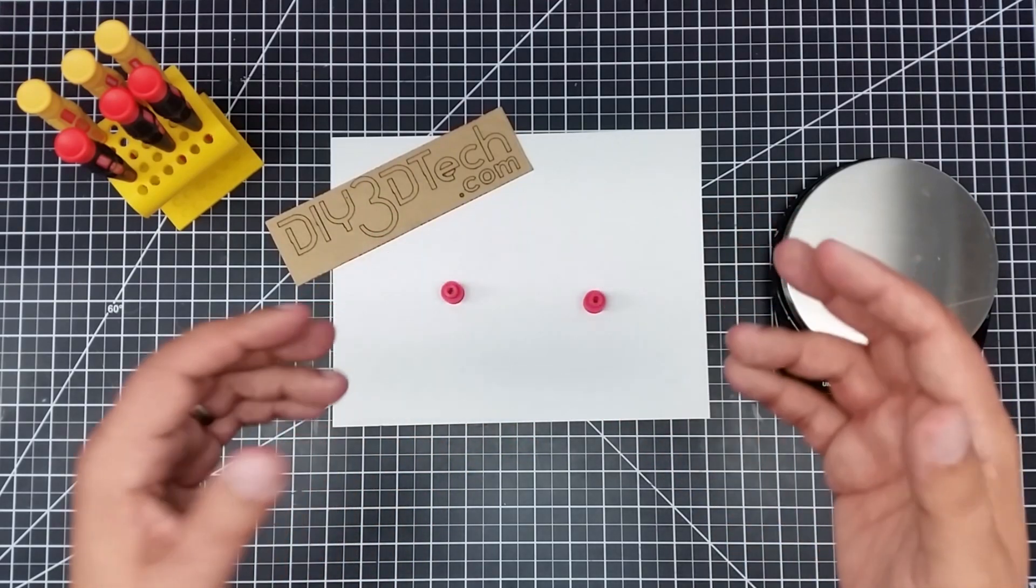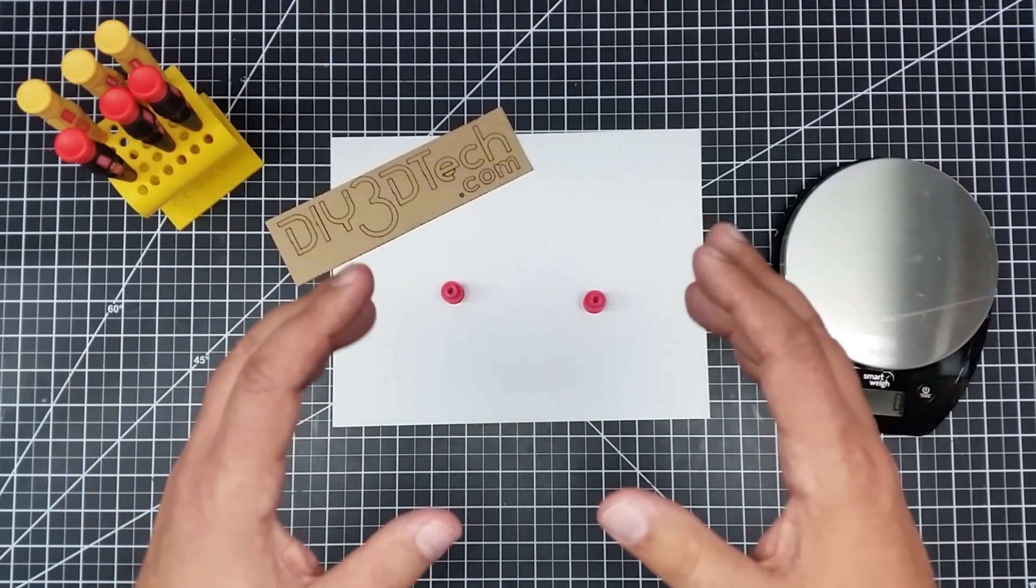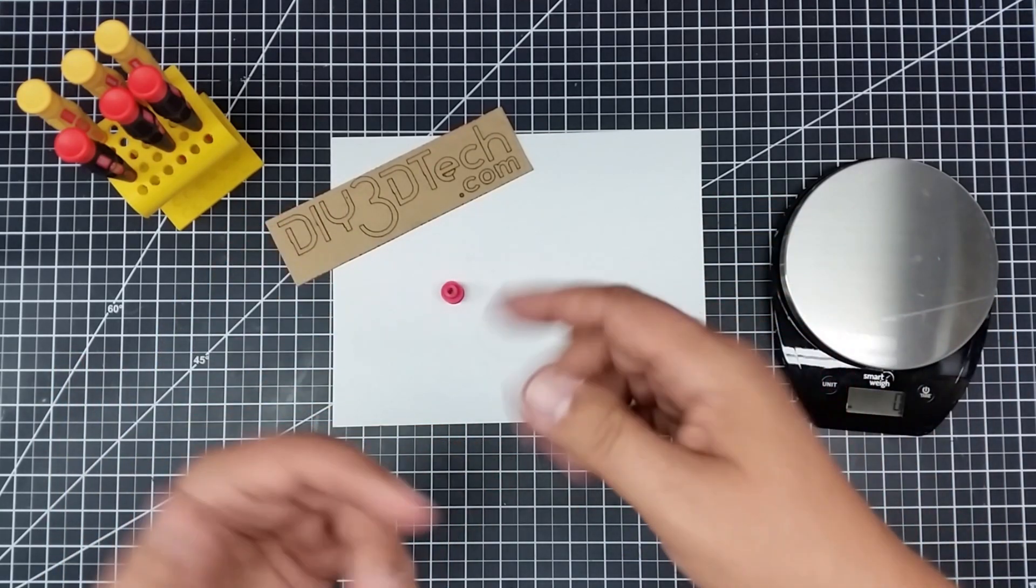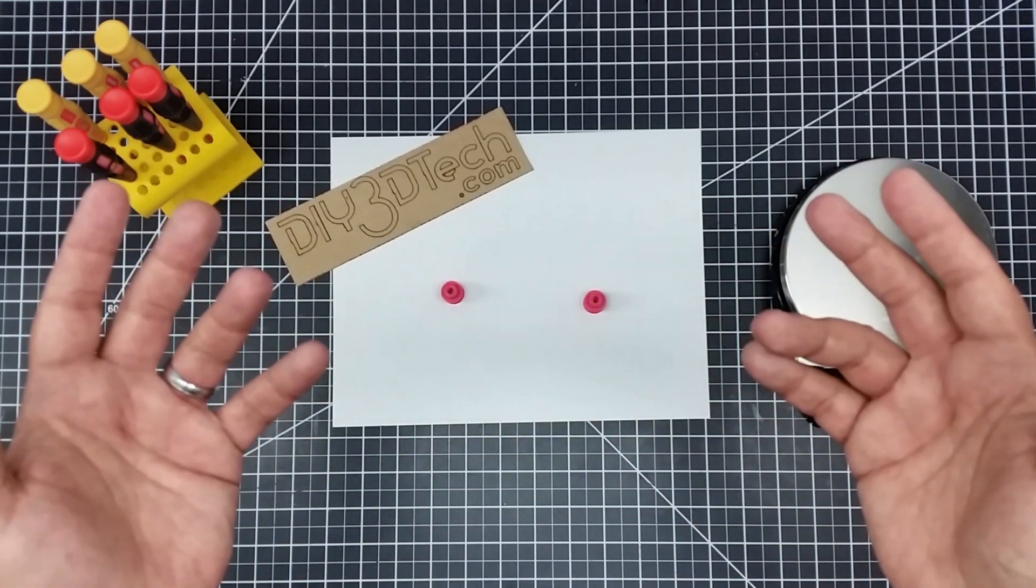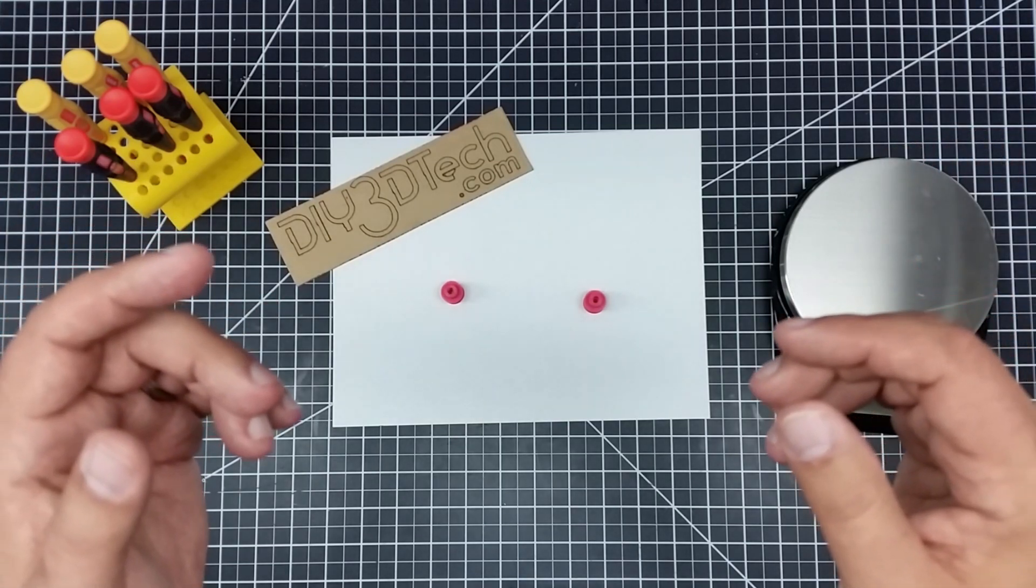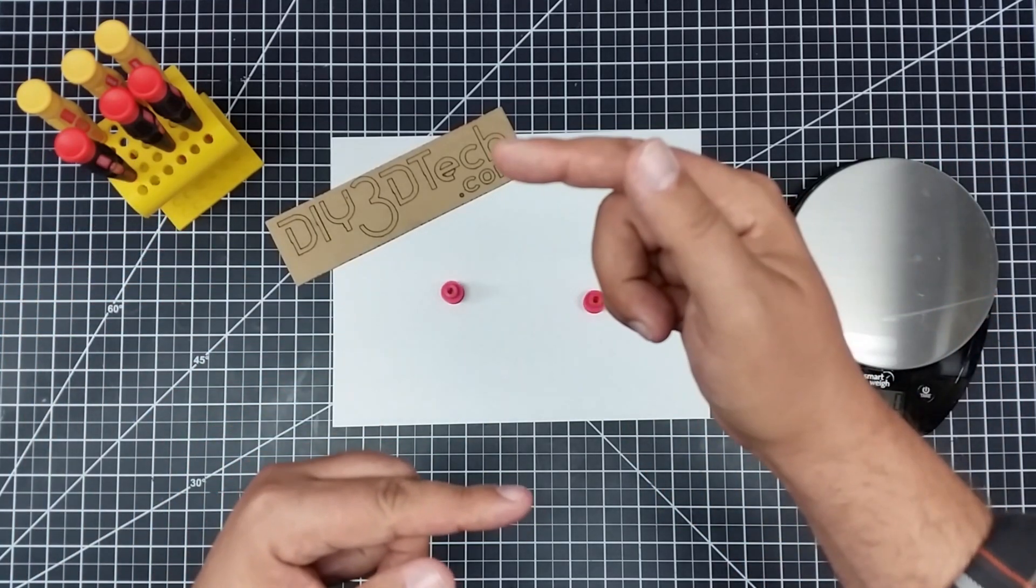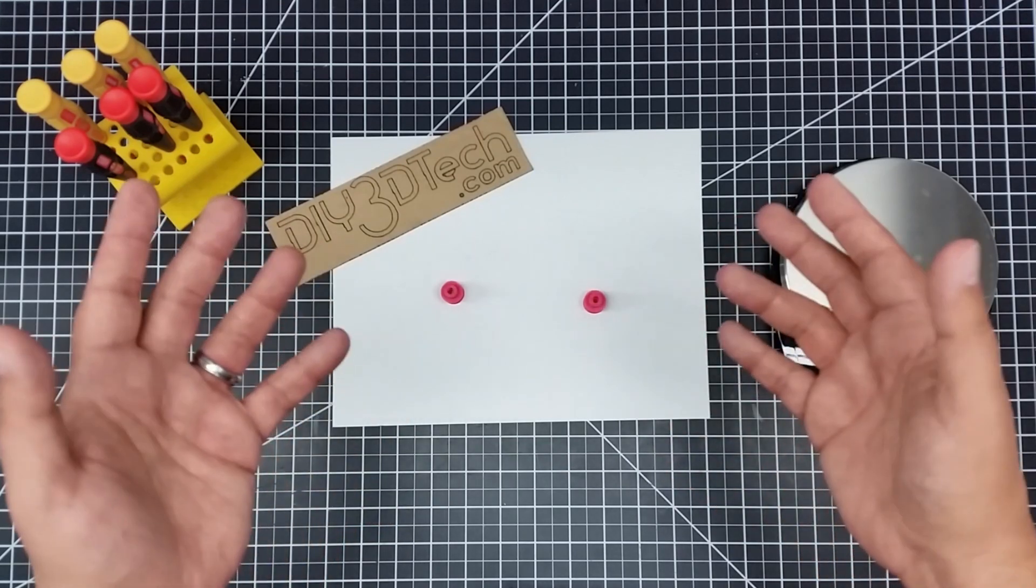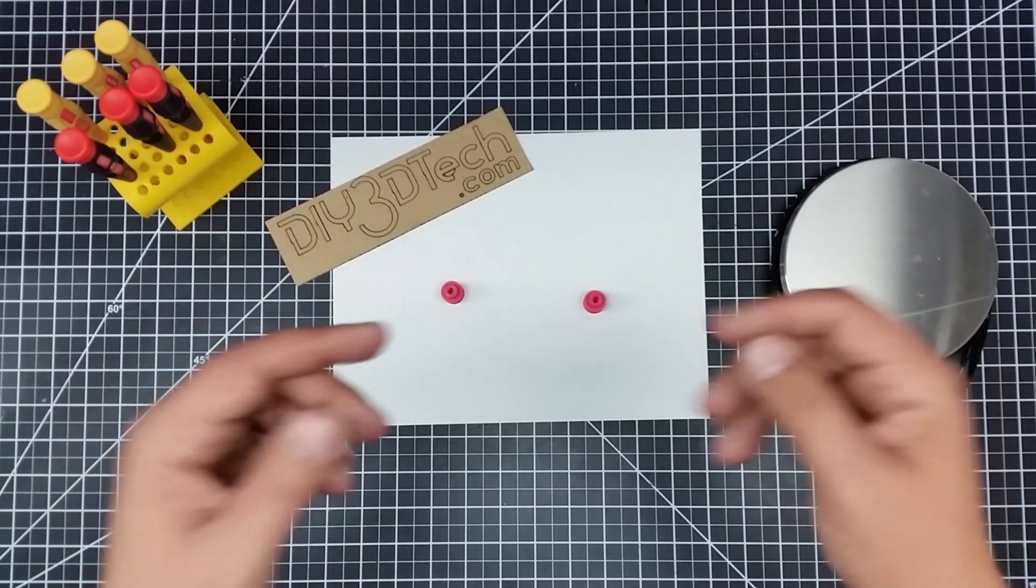To recap, one of the things that I did with this is, instead of just putting 999 like in the miniatures video, which maybe you could, I actually specified the entire width. So in this case, at 0.05 was I think 420 layers. So I specified 420 layers as being top layers.